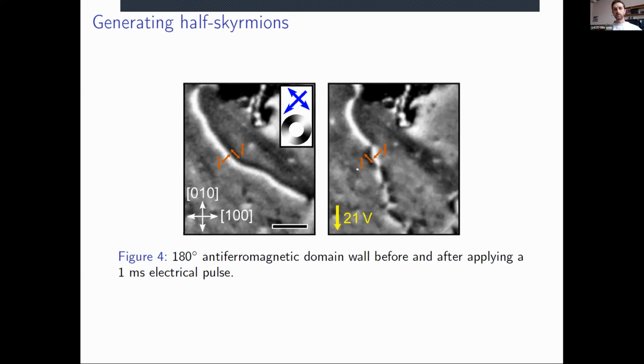I've highlighted another region here with the spins showing the Néel vector alignment. And you can see that the contrast has swapped from being previously white to black, to in this section being black to white. So that's what corresponds to a chirality reversal of the domain wall. And it's actually the pinch points at which the chirality reverses that we're interested in.